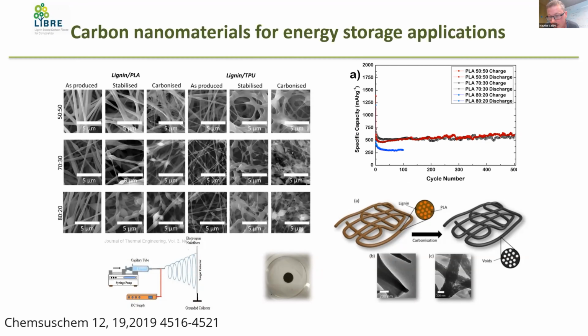The typical material now for an anode is graphite. It's fossil based, and it has a capacitance of about 300. Our sustainable carbon nanofibers were twice that, so they're twice as good. People always talk about sustainable materials and say that their function is a lot less than fossil-based materials, but these materials outperform fossil-based materials as well. So that's the key message.